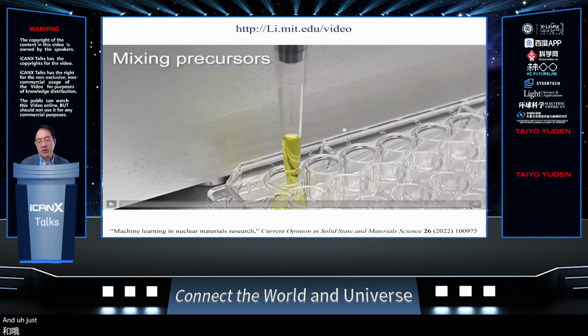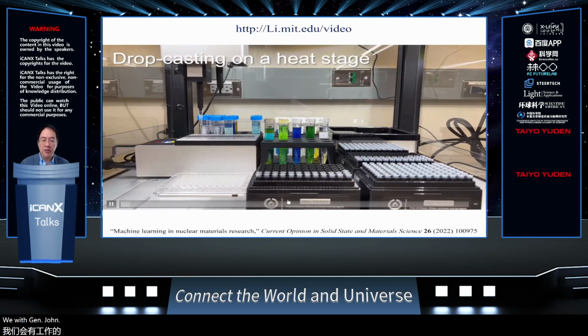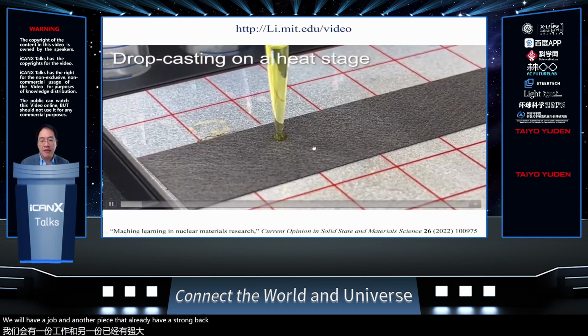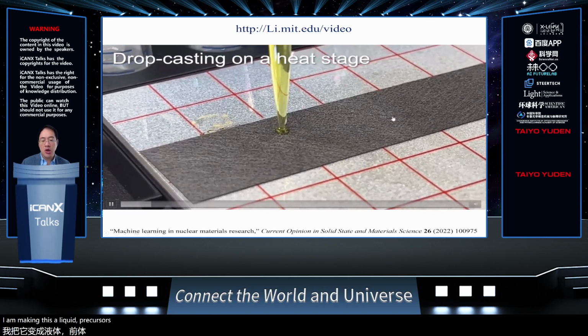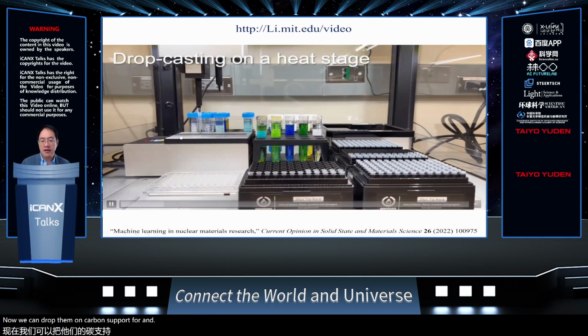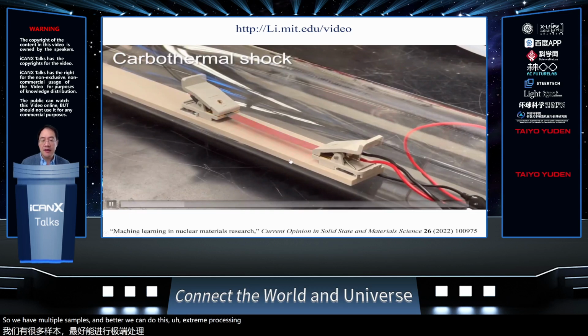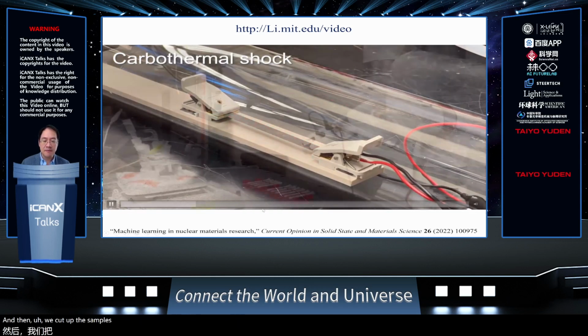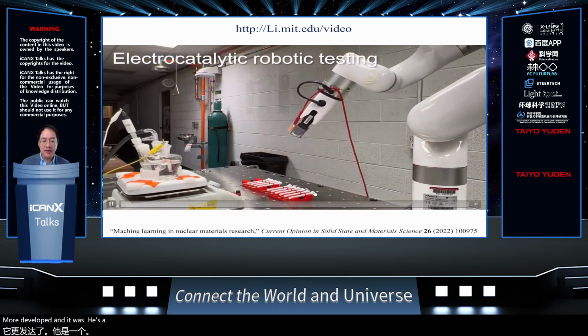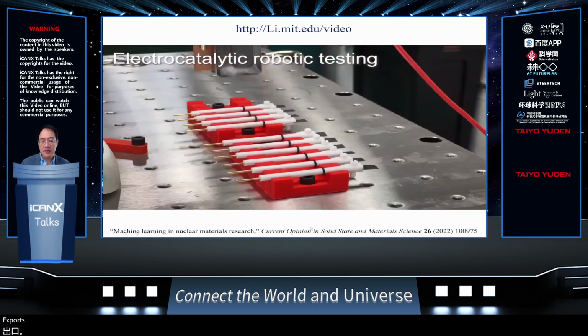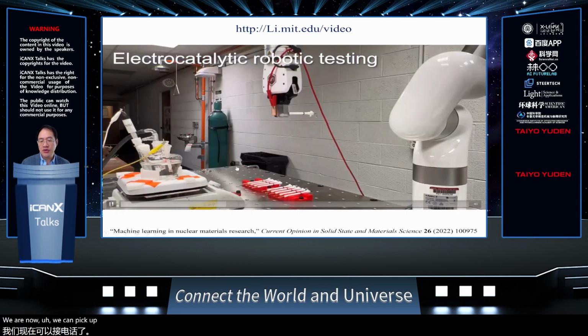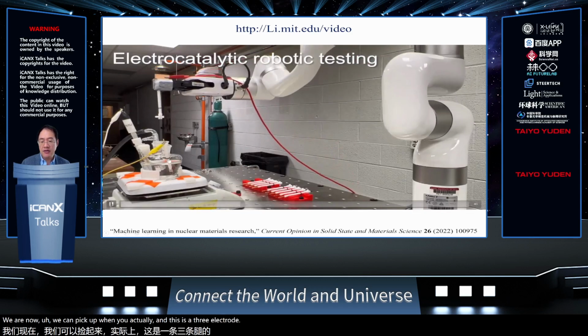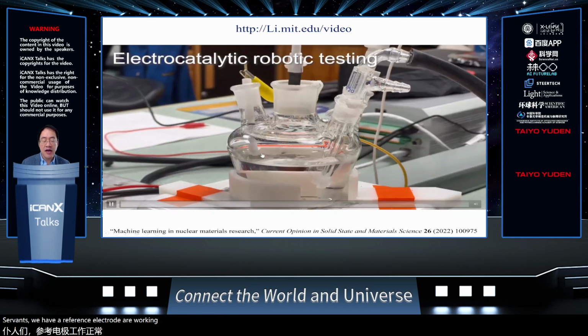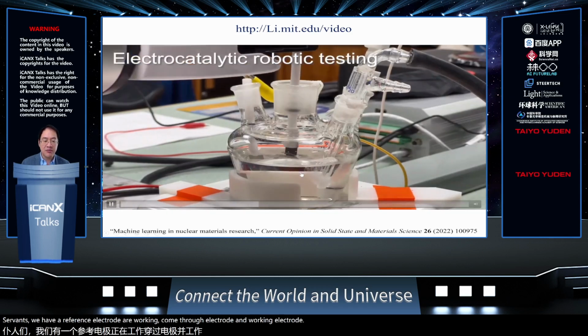And just in the last week, Zhichu, with Zhen Zhang and another postdoc, Ali, have shown that by making these liquid precursors, we can drop them on carbon support. We have multiple samples, and later we can do this extreme processing. Then we cut up the samples and load them into these electrodes. Now we can pick up one electrode, and this is a 3 electrode experiment. We have a reference electrode, a counter electrode, and the working electrode is dipped into the beaker.